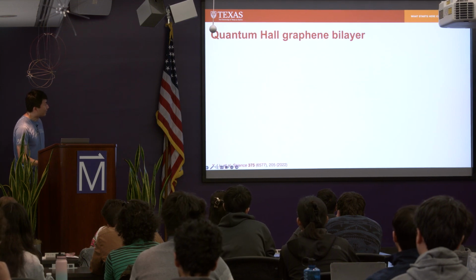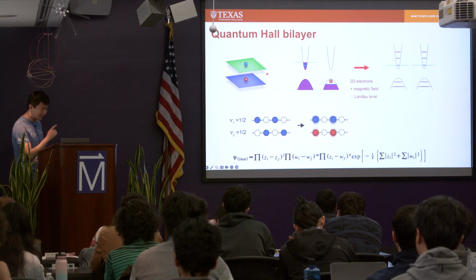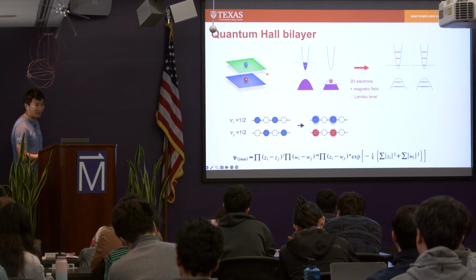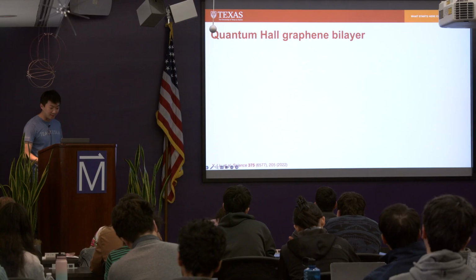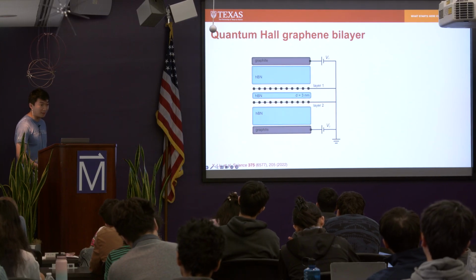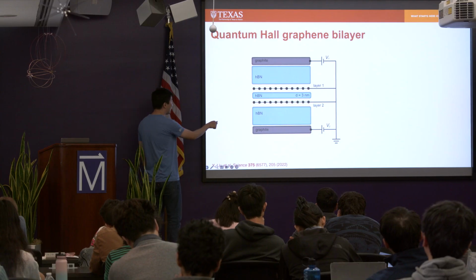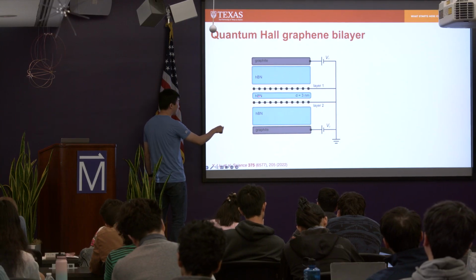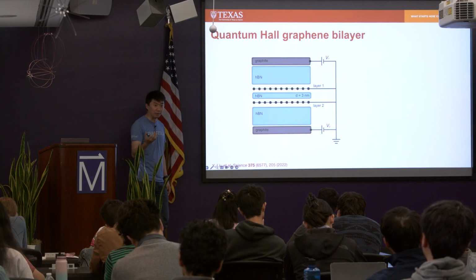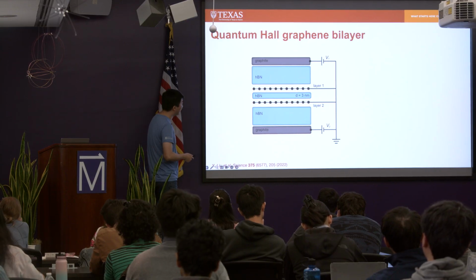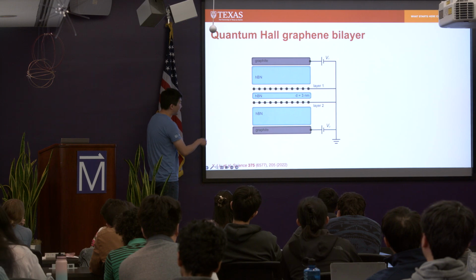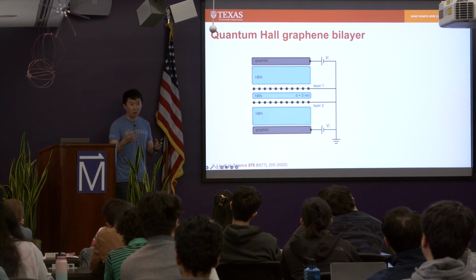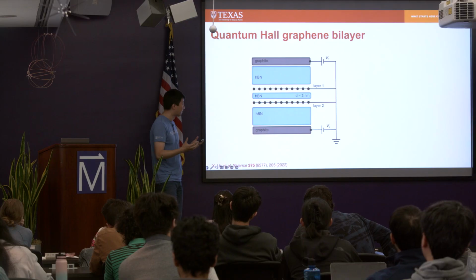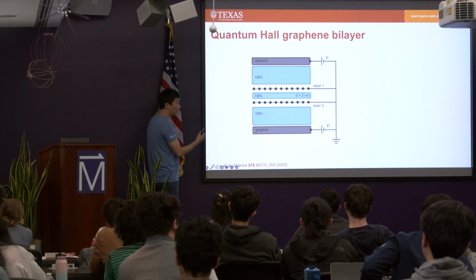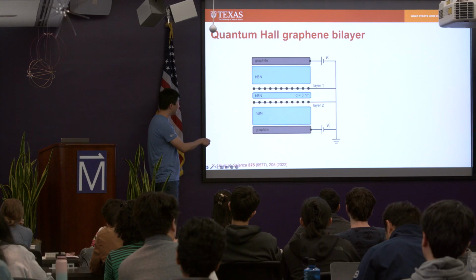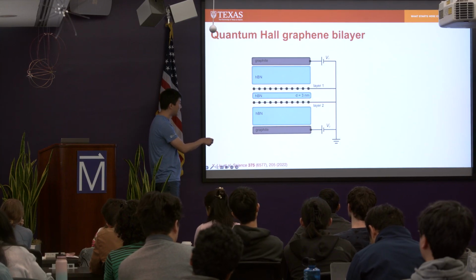Okay, so experimentally, in this picture, I'm just showing you 2 layers of electron without any structure. Experimentally, we realized this by doing a quantum Hall graphene bilayer structure. The most important part is 2 monolayer graphene that's separated by a hexagonal boron nitride that's about 2 to 3 nanometer, right? So hexagonal boron nitride is what we call white graphene. It has almost the same lattice structure, but it's completely insulating. At about 2 or 3 nanometer, this boron nitride is still fully insulating, meaning that there's no tunneling, right?